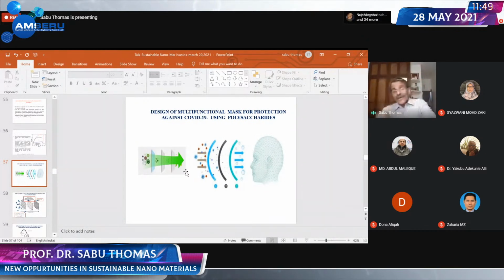If at all some coronavirus gets into your mask, this middle layer can kill it because it has positively charged nanocellulose. It can interact with the coronavirus, which has a protein envelope that is negatively charged. So it's an electrostatic interaction. Additionally, we also introduce curcumin.